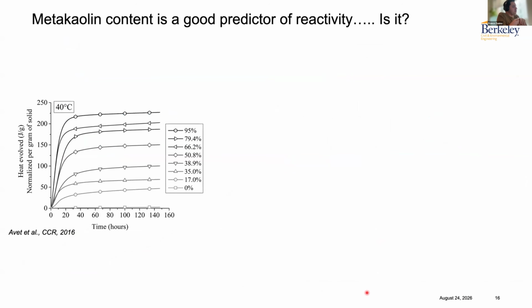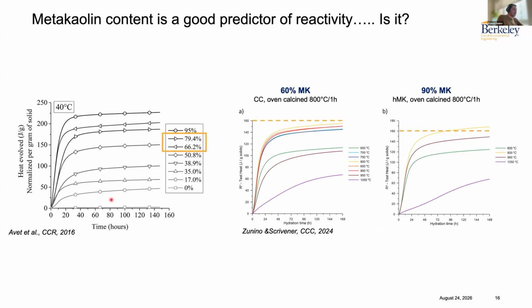And on this, there's been this idea or concept that metakaolin content is a good predictor of reactivity, and that we can use the kaolinite content of a clay to relate to the potential reactivity that that material will have. And the answer is that in general, that works, but here go a couple of exceptions. Look, for example, from the original R3 test paper, that these two curves are reversed. So the one with the lower kaolinite content actually exhibits a higher reactivity versus the other one.